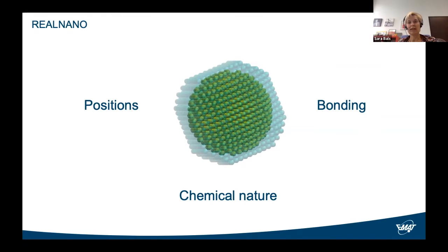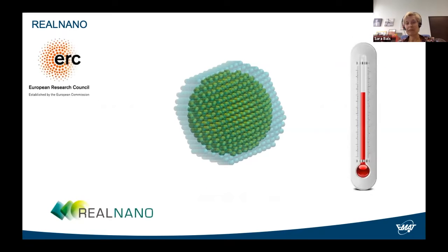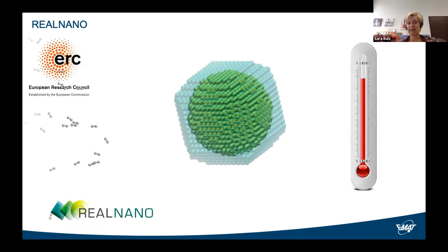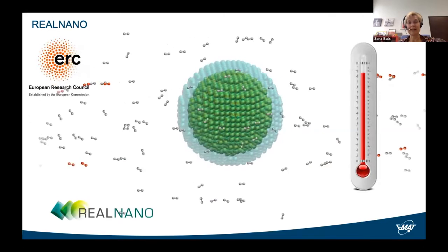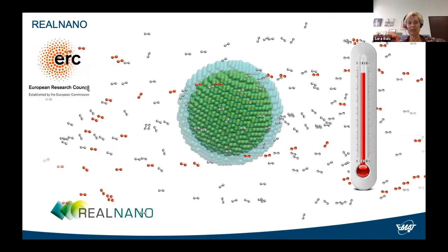However, we should not forget that all of these measurements have been performed under the conventional conditions of a transmission electron microscope, meaning room temperature and ultra-high vacuum. And those conditions are no longer sufficient if we think about the applications of these nanomaterials, and also when we think about capturing transformation of these nanomaterials. So a next challenge in the field of 3-dimensional characterization using electron microscopy is to again determine these parameters, but now at high temperature, or for example, in the presence of a gaseous environment. And that is exactly the aim behind the Real Nano project.